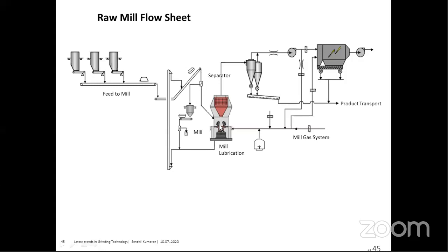Because the roller and the table will have a material contact, when we have metal inside the system, it disturbs operation, and in the case of a coal mill, it generates sparks and can even cause explosions. So we don't want any metal entry inside the mill. Through the metal detector and a gate, the metal is separated, and only the feed enters the mill. Then this is an external recirculation system, with a belt conveyor and a bucket elevator. It recirculates the material, and the fine product is collected through the product cyclones and conveyed through the product transport. This is the hot gas system, where the hot gas enters the system.